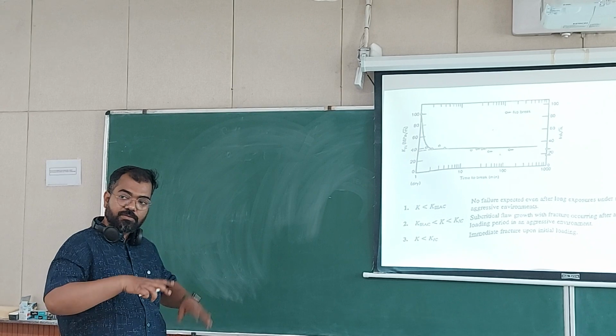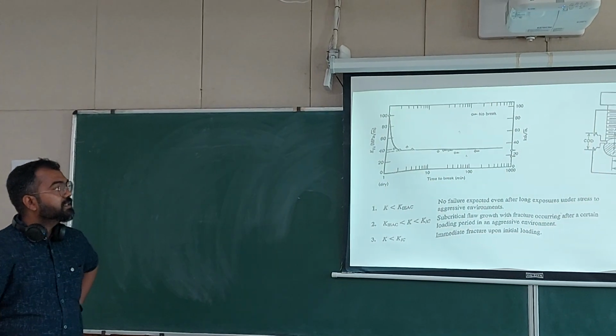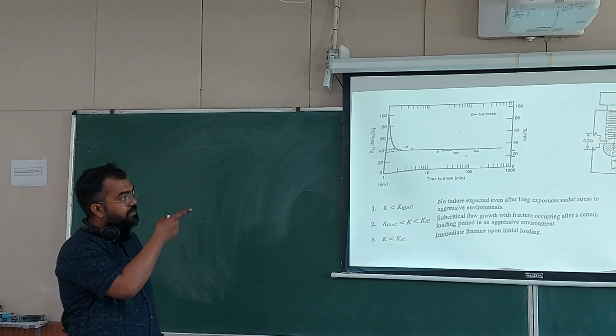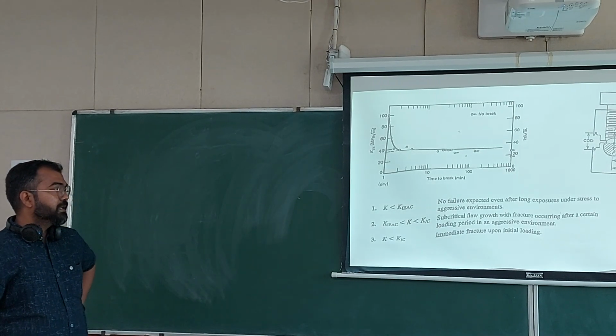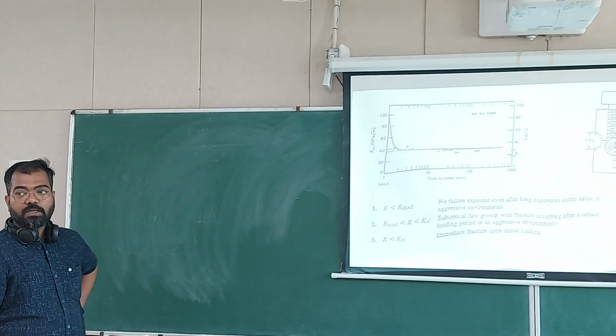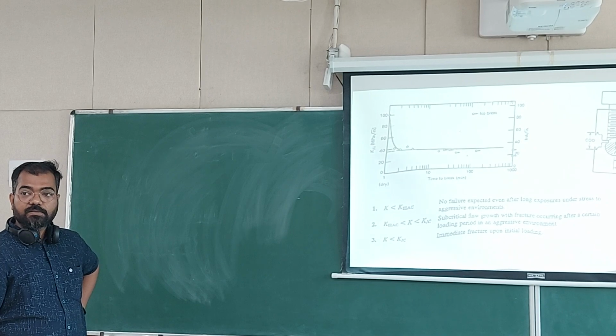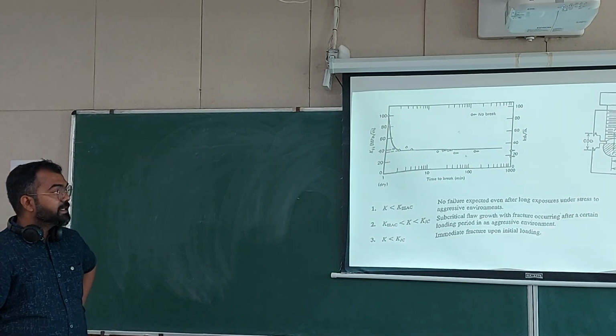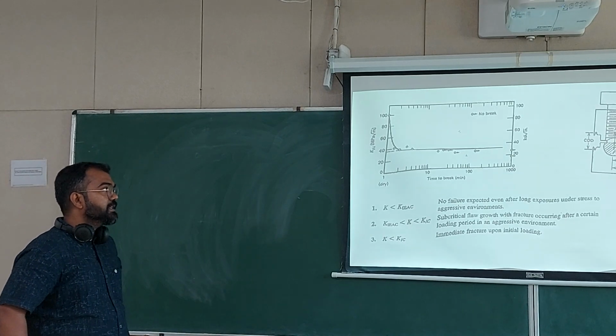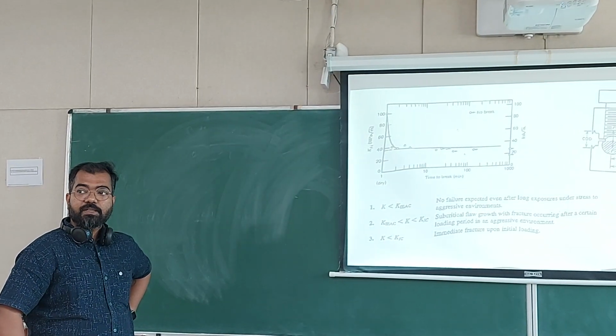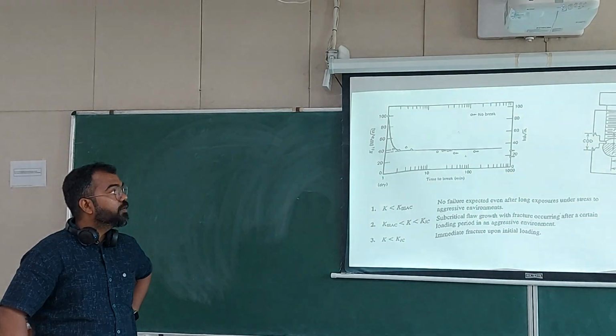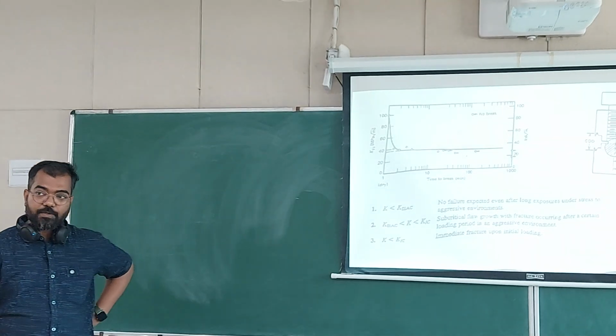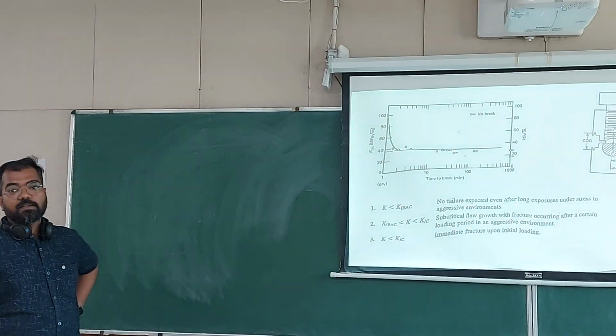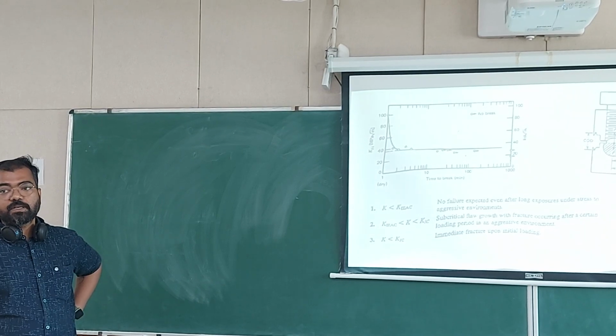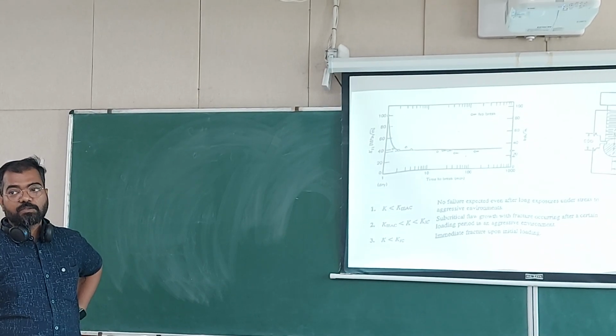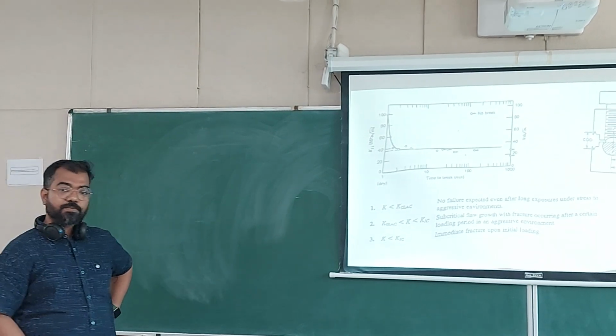This CT specimen was used in a fixture, and you can do all the instrumentation with this. You can put a COD gauge where you see the COD knife edges, and take the wires out and seal the wire so that it is not affected by the corrosive media. But then there is a problem that the corrosive media should not affect the loading screw. So you have to make a material which has a protective coating, or a material which does not corrode in the media where you plan to put your specimen.